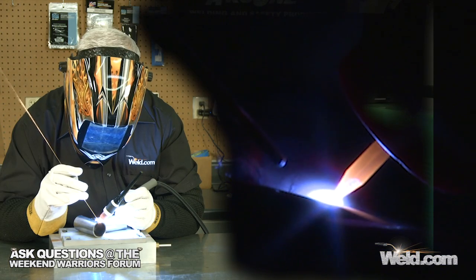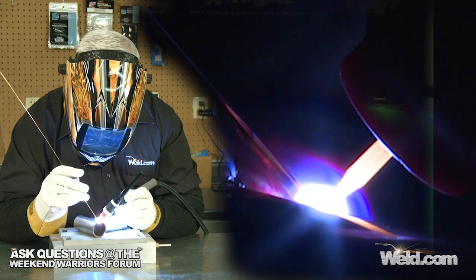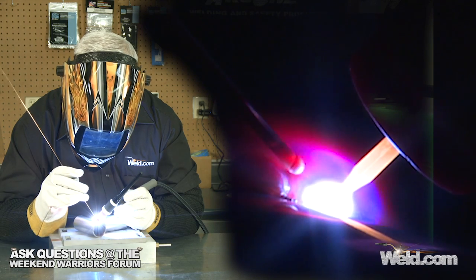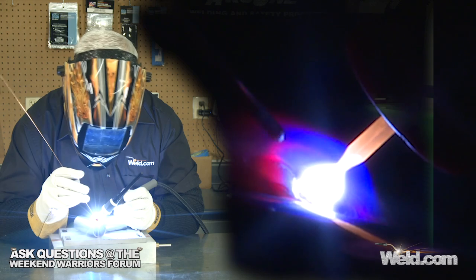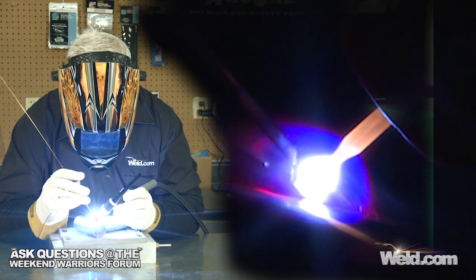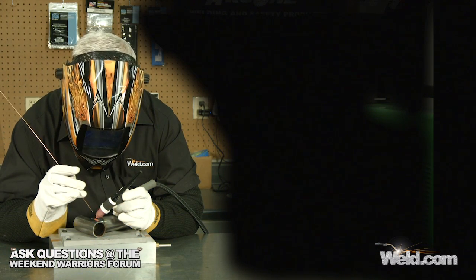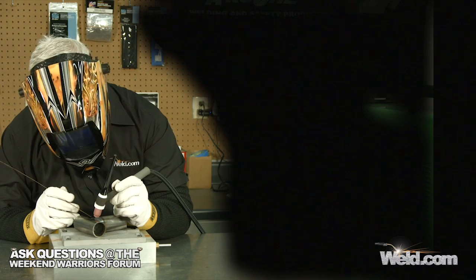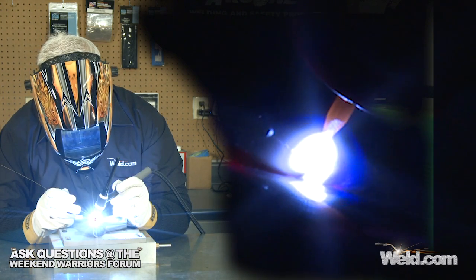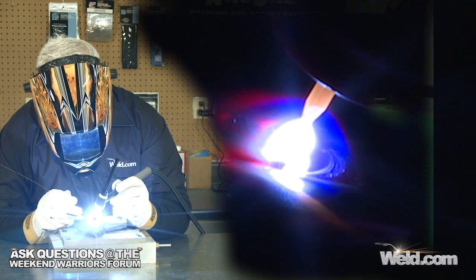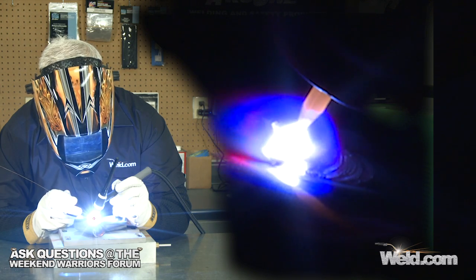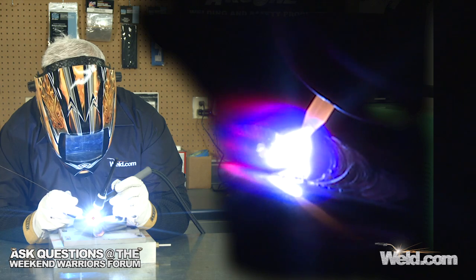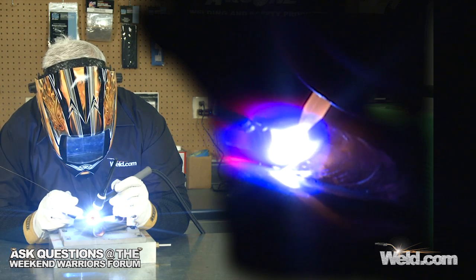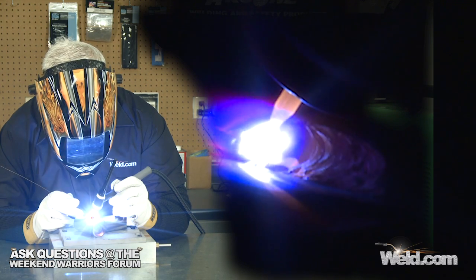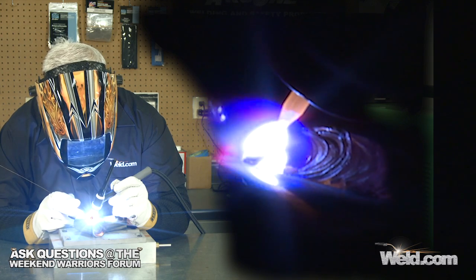Okay, I've already welded the sides up, so I'm just doing kind of an up and over wrap around using the TIG process. Tungsten size is still 1/16. I think the wall thickness on here is about 0.083. I'm using probably 70 to 80 amps, depending on what part of this wraparound I'm at. Filler material, I'm using the ER80SD2, which is the same thing that we use for 4130 Chrome Moly. See, it welds really clean, it wets out very nicely.